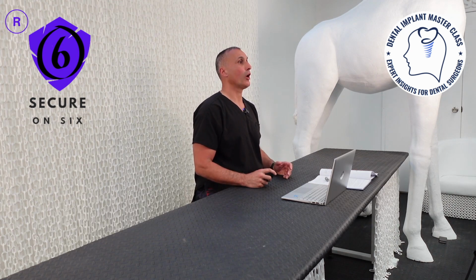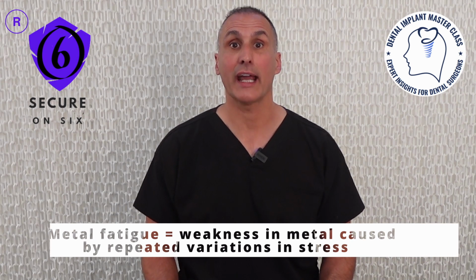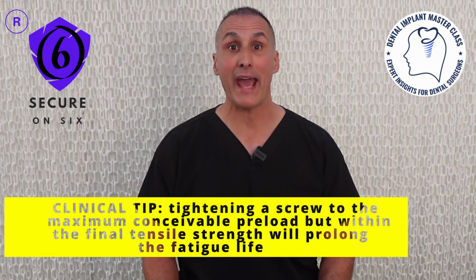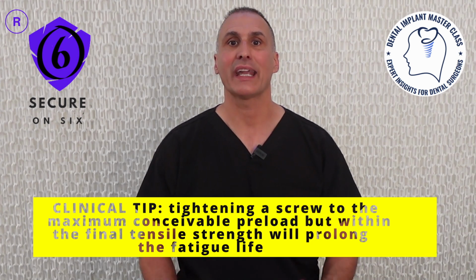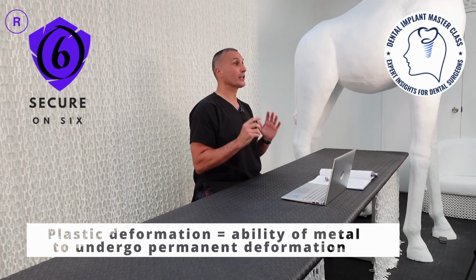Altering the chemical composition of an alloy in an abutment screw and using dry lubricant coated screws can achieve higher preload. Materials with low strength, like pure gold, can serve as an effective dry lubricant. Gold-coated abutment screws have been shown to maintain higher preload compared to non-coated screws. Metal fatigue, which results from cyclical loading and gradual structural damage, is a frequent cause of implant failure. Tightening a screw to the maximum preload within the material's tensile strength can extend its fatigue life, but over-tightening can lead to plastic deformation. Precision and quality in the machining of the implant components affect metal fatigue and the contact precision of the parts during the application of the ultimate torque.